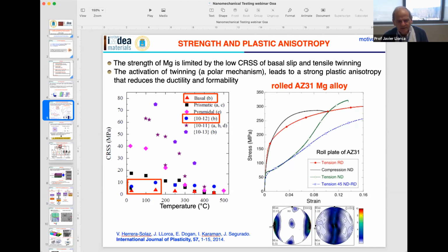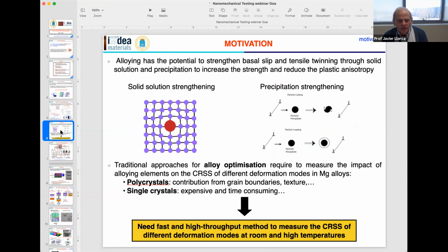You would like to increase the critical resolved shear stress for basal slip and for twinning, and decrease the critical resolved shear stress for pyramidal slip, in order to have a material that is more homogeneous or less anisotropic from the practical viewpoint, and then to have higher formability and to enhance the use of magnesium alloys for different applications. So how do you do that? Well, obviously, alloying has the potential to strengthen basal slip and tensile twinning through solid solution and precipitation hardening. And you know very well that in the case of solid solution, you just put some strain in the lattice, or in the case of precipitates, the precipitates are obstacles to dislocation motion. So what you have to do is try different alloying elements to increase the critical resolved shear stress for basal slip and twinning.